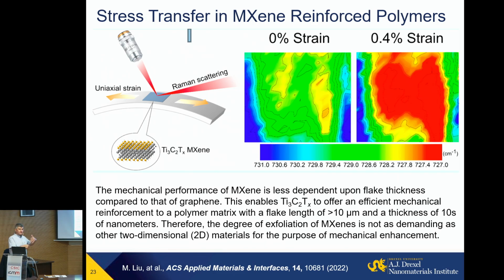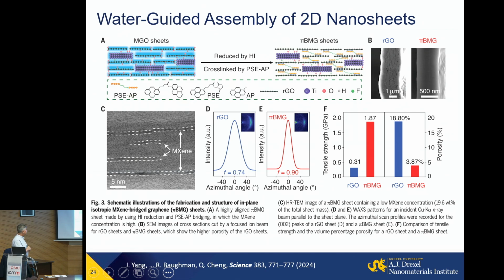And they have very good load transfer because of surface functionality, much stronger interaction with polymers, so you can have smaller flakes or a small amount of material intercalating. This is work with Ian Kinloch from Manchester, from the Graphene Institute here. And people also start assembling them with other materials. This is not our work. This is a work from the Chinese Academy of Sciences, and Ray Baughman from UT Dallas, published in Science a couple of months ago. They combined MXene with graphene oxide, cross-linked by organic aromatic molecules to achieve pi bonding and electronic conductivity, reducing graphene oxide with HI, making RGO.